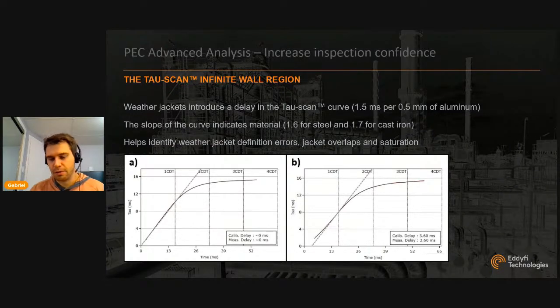And typically, you'll get 1.5 milliseconds of delay per half millimeter or 20 thousandths of an inch of aluminum. Stainless steel is going to have very little effect. It's not going to introduce a delay typically. And galvanized steel or carbon steel weather jackets are going to introduce some delay. The slope of the curve indicates the material. So we have two algorithms within the Lift system, one that considers a slope of 1.6 for steel, 1.7 for cast iron. So this is what you're seeing here. So that slope that we're referring to, with a reference dashed line here, is characteristic of the material. If you're scanning the wrong material, with a steel setup on cast iron, for example, you'll see that slope have a different angle.